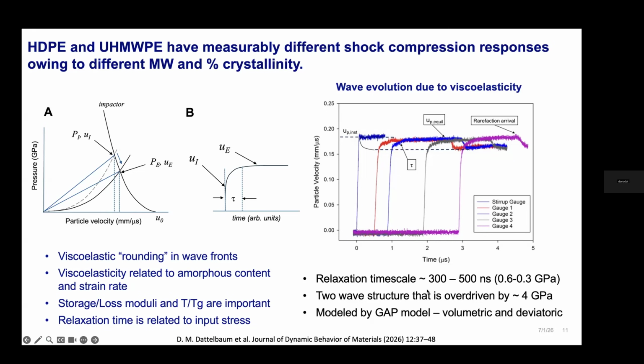One of the things I will note is that that two-wave structure associated with viscoelasticity is basically overdriven by about 4 GPa, or 40 kilobar. So what that tells us is that the viscoelasticity really dominates at these semi-low strain rates, still 10 to the fourth, 10 to the fifth per second, but lower pressures. And the relaxation time can be somewhat significant.